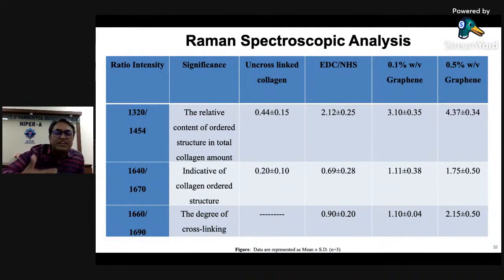So we looked into the ratios of various intensities, which is a usual way of looking at the orderliness of the collagen and how much the collagen structure is ordered. You see more ordered collagen is present when 0.5% graphene is incorporated.